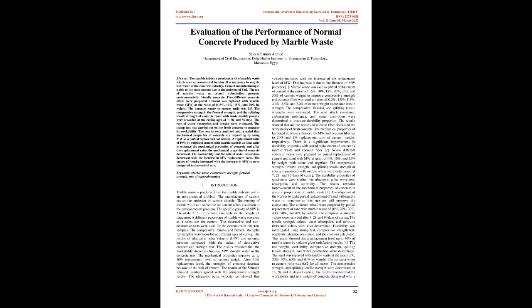The destructive and non-destructive tests were used for the evaluation of concrete samples. The compressive, tensile, and flexural strengths for samples were recorded at different ages of curing. The results of ultrasonic pulse velocity, UPV, and rebound hammer were compared with the values of the destructive compressive strength test. The results revealed that the workability decreases because MW absorbs water in the concrete mix. The mechanical properties improve up to 10% replacement level of cement weight. After 10% replacement level, the strengths of concrete decrease because of the lack of cement.